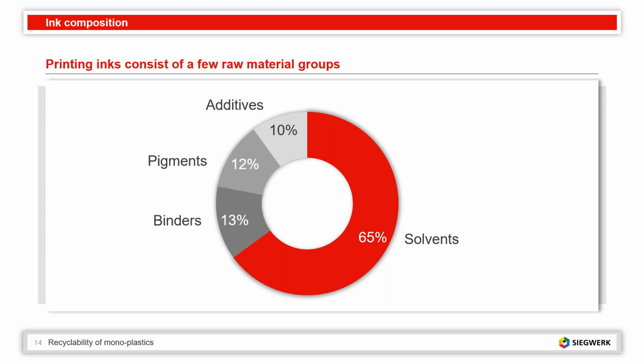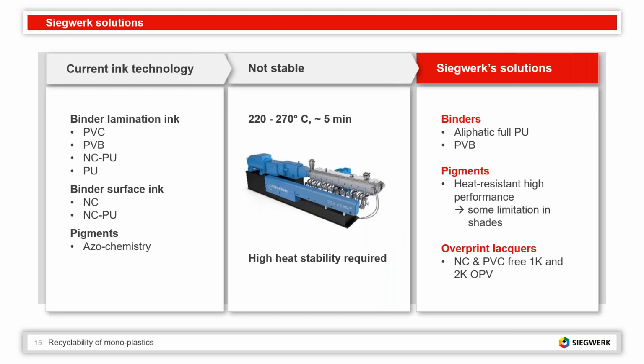And now if we look into inks which are used today, you can see on the left-hand side, for the well-established standard current ink technology for packaging material, for lamination, there's a variety of binders like PVC, polyvinyl chloride, polyvinyl butyral, then nitrocellulose, polyurethane inks, or even full PU inks. If you look at the surface printing inks used today, you see that nitrocellulose is again very important for this approach, sometimes in combination with polyurethanes.